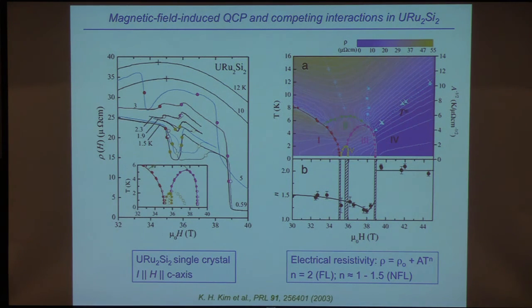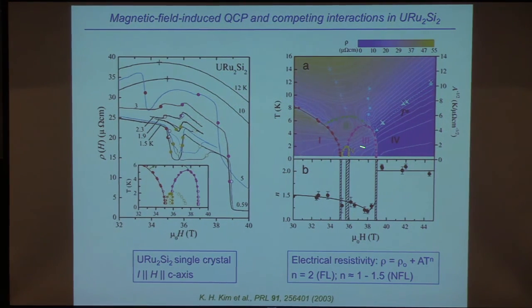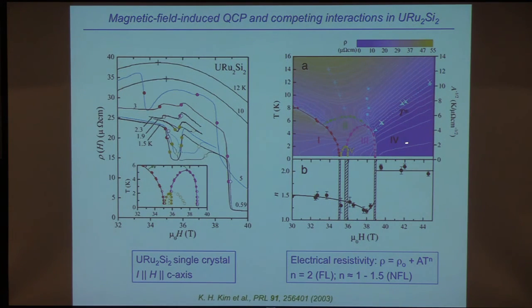From the overall study, what they found was this more complex situation right here. This is the suppression of the hidden order phase, and then you see a cascade of other quantum phases that occur in this region right here. There's a metamagnetic transition right here, and this is the maximum in the resistivity that marks the coherence temperature, and it appears to terminate at a quantum critical point right here. Then you get a line emanating from that point along here where you cross over from non-Fermi liquid behavior to Fermi liquid behavior. In this region you see the exponent of the resistivity is about 1.5 throughout these phases, so that's non-Fermi liquid-like, and then when you cross over into this region it jumps up and becomes Fermi liquid-like right here.